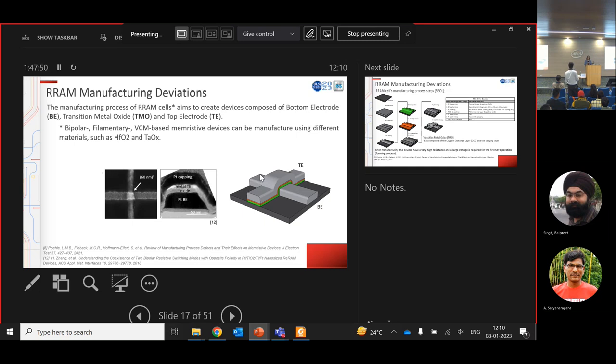Well, you are going to have a level of density when you use it as a memory element. And for spiking, you need the analog, you need the multi-levels. Here, I already saw some work with seven levels, but then they analyzed the reliability, and at a certain point you cannot distinguish more than four. Four is really optimistic, because you have this variability and the intervals are really close, so I cannot say what the real density is for this. I don't think that we have that yet.